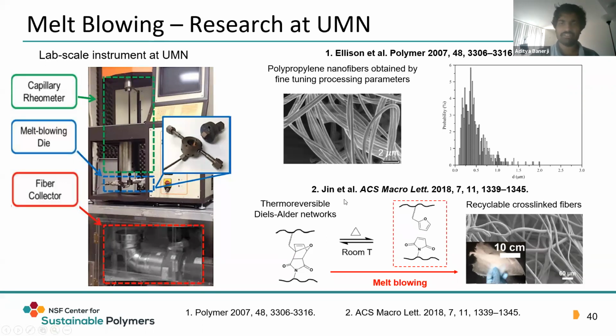In addition, a recent paper highlighted that using a polymer functionalized with a thermoreversible Diels-Alder network can provide a method to get recyclable cross-linked fibers, which also leads to a sustainable aspect of this technique.